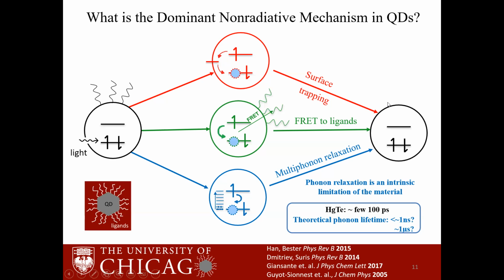But there are other quantum mechanical calculations which predict that the phonon relaxation rate should be slower than microseconds. So this is a really important question, whether phonon relaxation is really as fast as a nanosecond. Because if it is, then it tells us that for our quantum dots, the relaxation rate is only 10 times faster than the fundamental limit. And this tells us that we cannot improve the performance of the detectors much more than